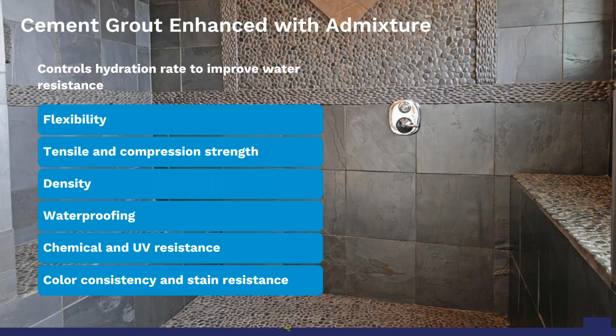It also adds more flexibility, more tensile and compression strength, density, waterproofing, chemical and UV resistance. So UV resistance meaning the sun coming through, say, a window. And the color consistency and stain consistency is improved when you use an admixture. There are select admixtures that can increase the ANSI standard of a cement grout. So it can exceed an ANSI 118.6 and a 118.7 if the powder mix you currently have does not meet those standards.